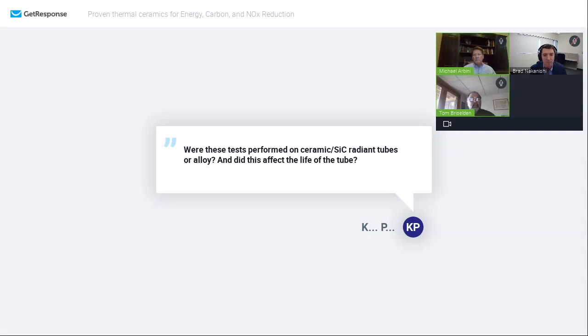So most of the applications where we've applied the spiral core and even the heat core technology have been on metallic radiant tubes or alloy radiant tubes, high nickel chrome alloys. And that's really our primary focus. Now, there have been some early developments in using spiral core in ceramic U-tubes. To my knowledge, there's only about 10 of those out in the world. But they work in either system. So they work in both metallic radiant tubes as well as ceramic radiant tubes.